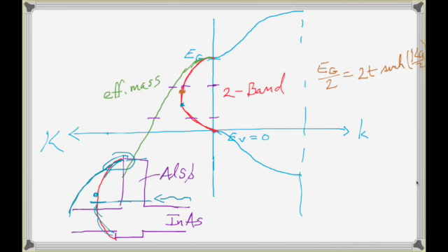Form your block sum, one block sum for each orbital, and so your basis in K space for each K is two orbitals. And you can solve each K all by itself, giving you a 2 by 2 Hamiltonian that's K dependent, and calculating the eigenvalues of that, we get our E versus K relationship. So that's what we've done so far, and now it's time to start going beyond into a real crystal.